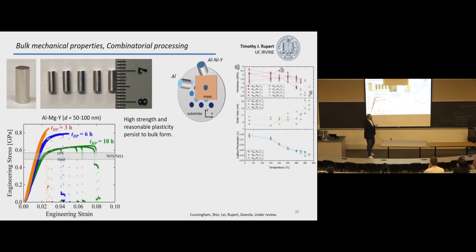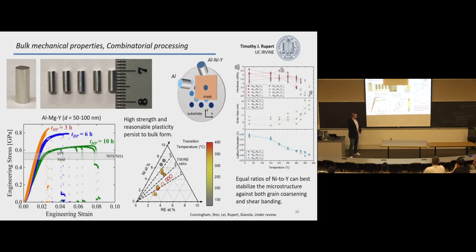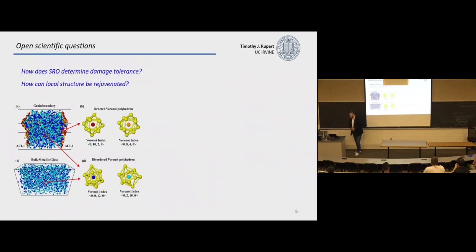And he's doing relatively quick experiments, measuring things like hardness and grain size and lattice parameter as a function of annealing temperature. But the reason he's doing this is he can then get some data that he can put on the ternary phase diagram, and for example, find that your transition temperature, so where you start to get evolution of the microstructure, is higher, which is what you want, near 1-to-1 than it is at 5-to-1. So he's able to basically tell us how much nickel to yttrium ratio we want to have.